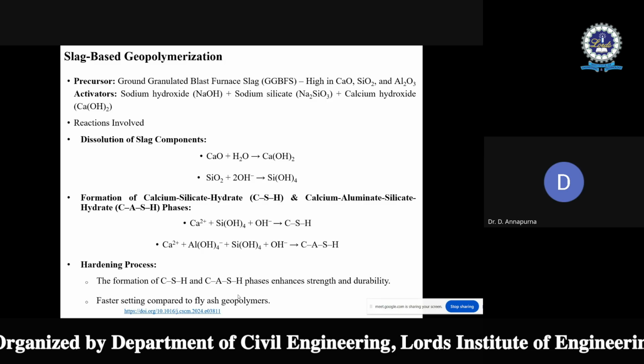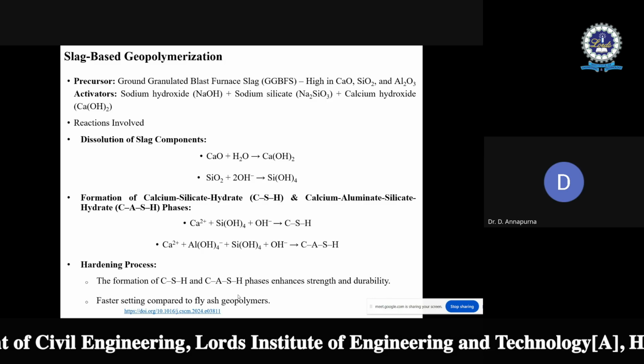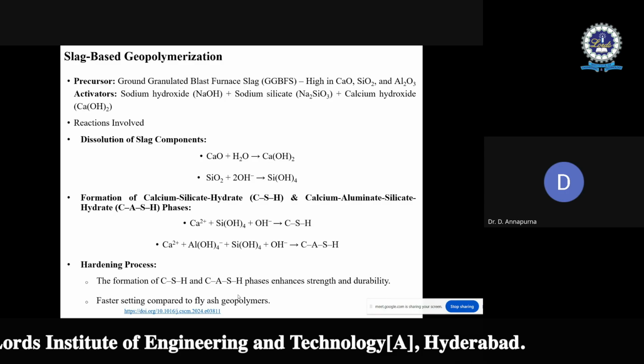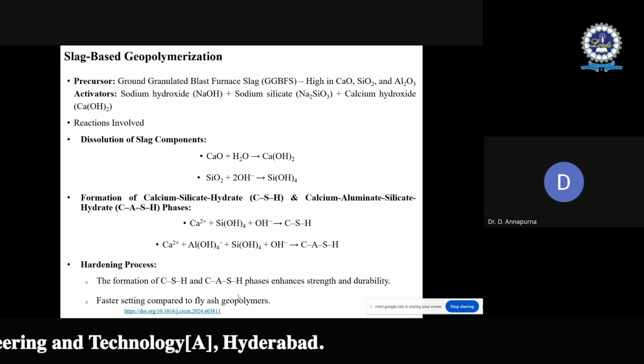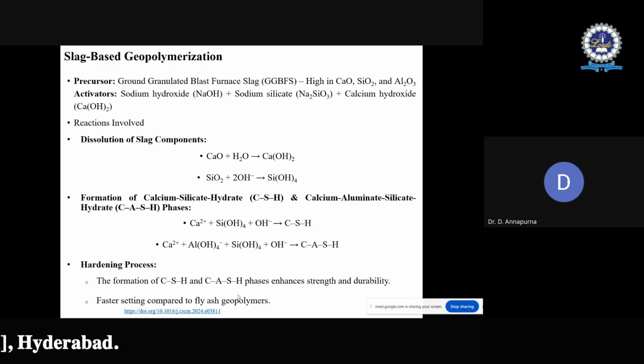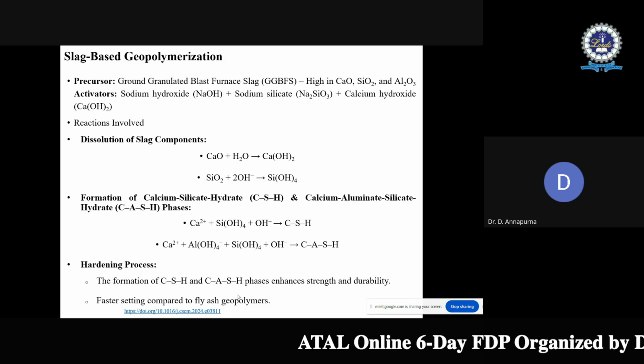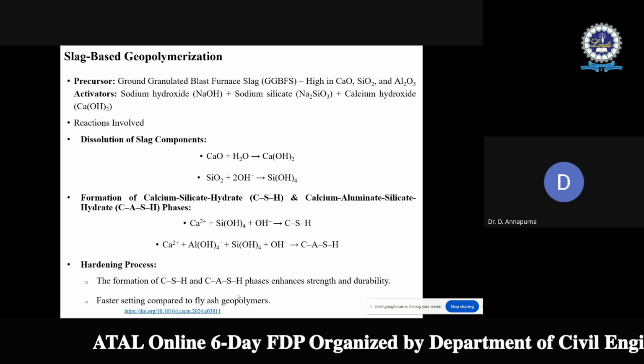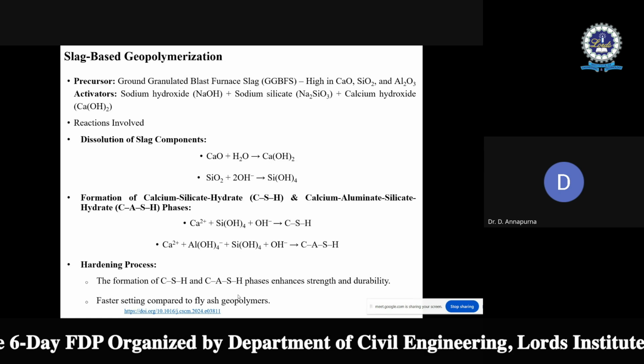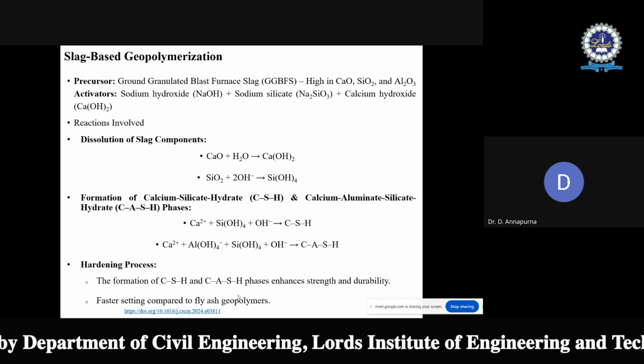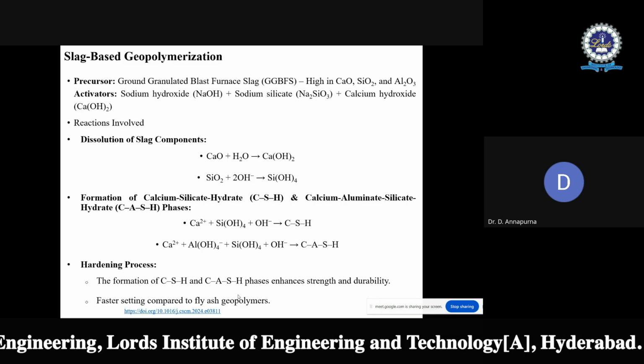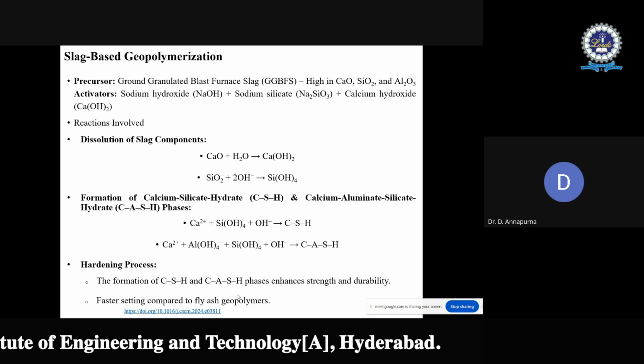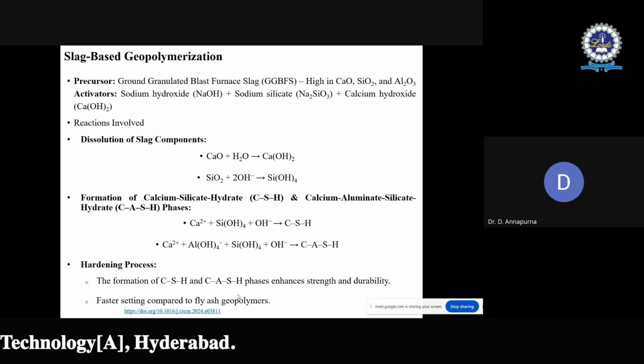When it comes to GGBS, when the GGBS is added in different proportions, the setting time rapidly decreased, like from 2 days to 1 day, then 60 minutes, then 45 minutes. That is the reason GGBS can be taken as a better material in geopolymer concrete, as an admixture to fly ash based geopolymer concrete.